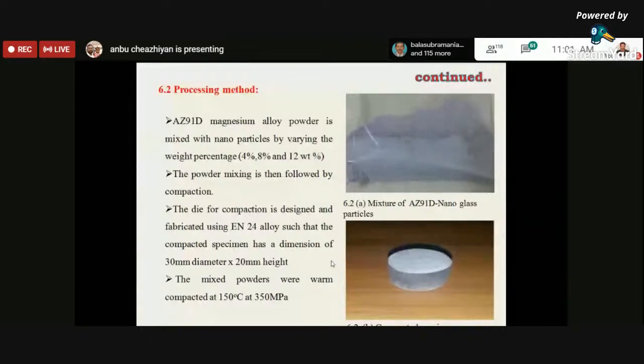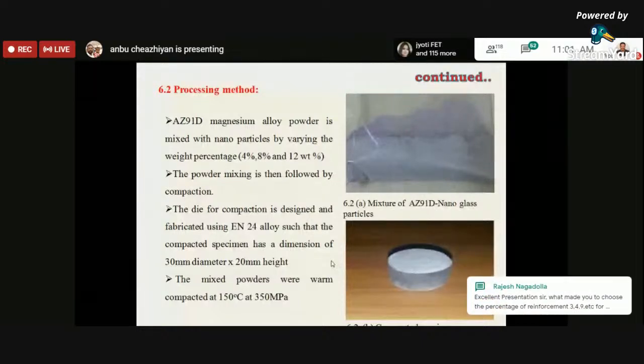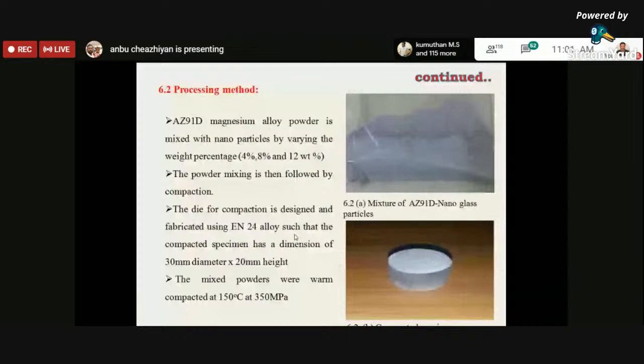So that the atoms get diffused. So we go for warm compaction, and hence, due to warm compaction, the reinforcement particles are able to hold with the matrix materials. Here I have used a compaction pressure of 350 megapascal. The warm compaction temperature is 150 degrees centigrade. So this is the sample that we have obtained.